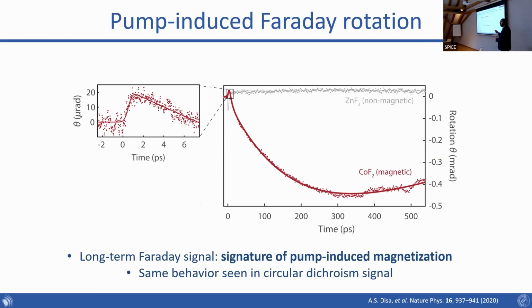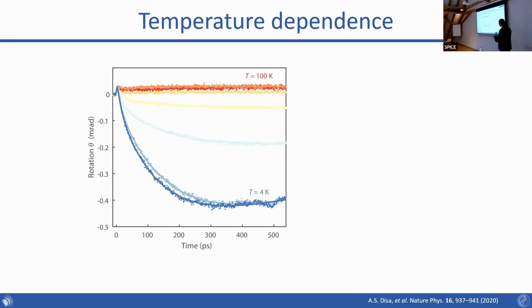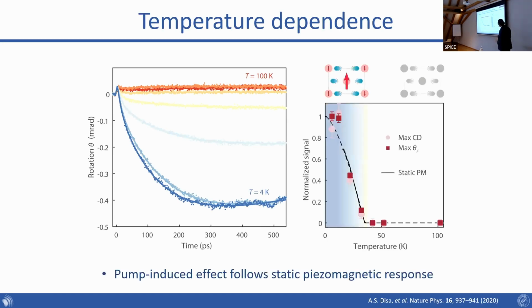And now we can look at what happens as a function of temperature when we excite this, going from, let's say, 4 Kelvin up to 100 Kelvin. Remember, the Néel temperature is 38 Kelvin. And when we plot then this sort of saturated value of the rotation angle or the circular dichroism, we can see that it goes away basically right at the Néel temperature. And then the temperature dependence, if you look below Tn, follows pretty closely the static piezomagnetic response in cobalt fluoride. So this is somehow a confirmation that we're driving something which is similar to this piezomagnetic effect, but we're doing it dynamically using light and by driving phonons.